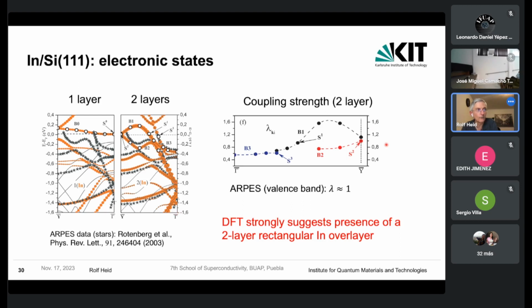We could also go further and look at the individual coupling strengths of certain electronic states close to the Fermi surface. We have done that in an extensive way, but from the experiment, we only get the information that the coupling of some states in the vicinity of the Fermi level should be of the order of 1. And we find, of course, a variety of coupling constants ranging around this lambda equal 1 value, but with quite a large spread. But in that sense, we are still in agreement with the observed coupling strength in ARPES.